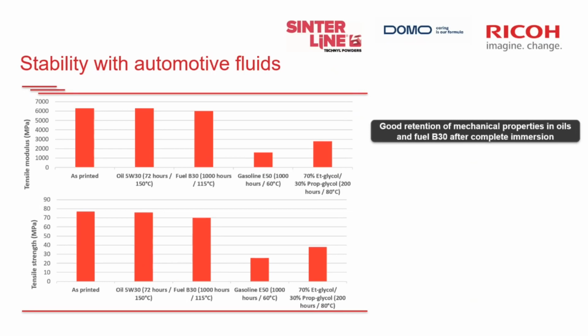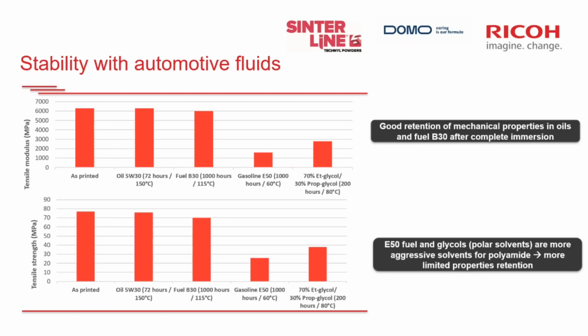As mentioned before, on top of the very good mechanical properties, the material also demonstrates good resistance to automotive fluids, such as oils and fuels, for example. The two graphs here illustrate the tensile modulus and the tensile strength of the material and how they are affected after aging at high temperature in different fluids. As you can see on the left-hand side, fluids such as oil or biodiesel don't really affect the mechanical properties of the components much. However, as you can see on the right-hand side of each graph, polar solvents like ethanol 50, gasoline or glycols are far more aggressive towards polyamide 6. So this leads to a more limited retention of the mechanical properties after aging.